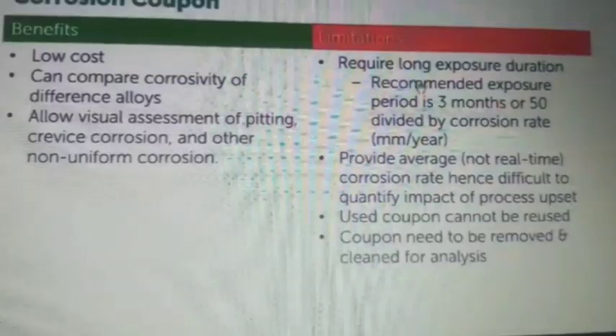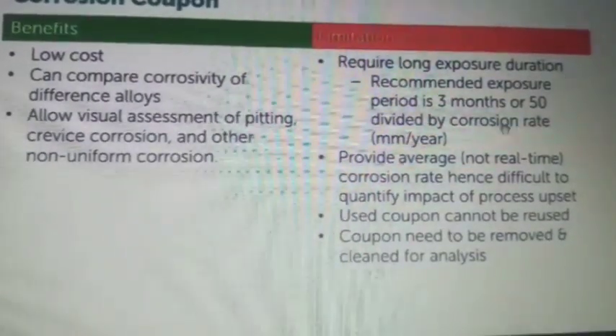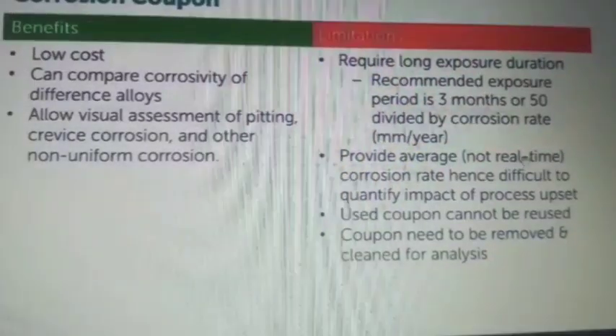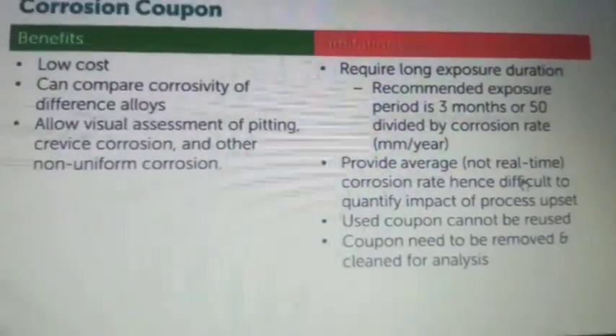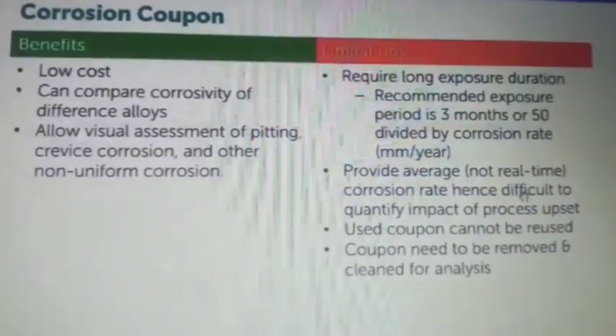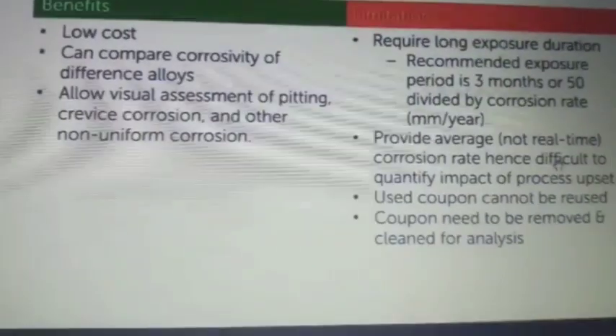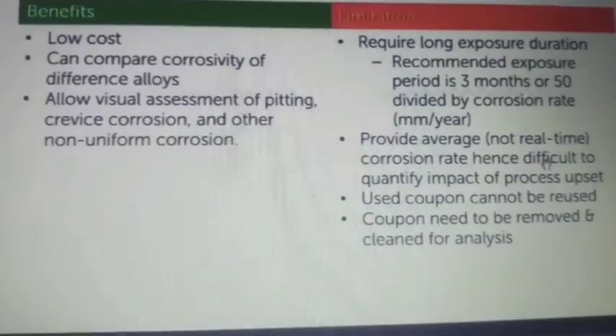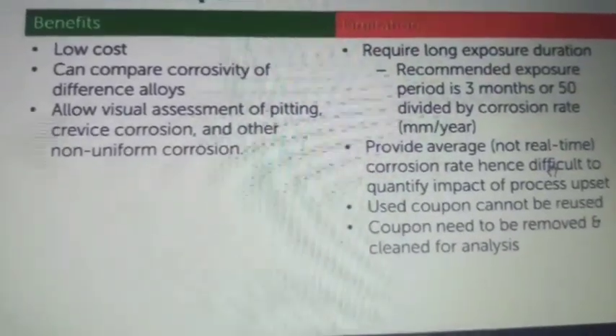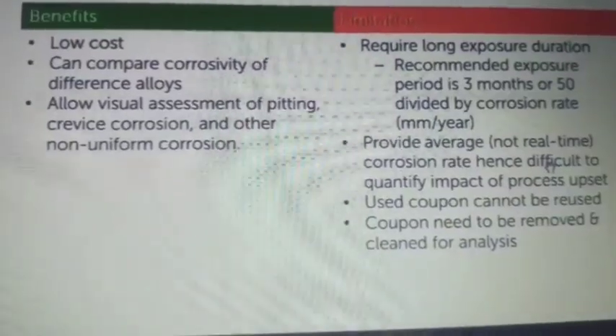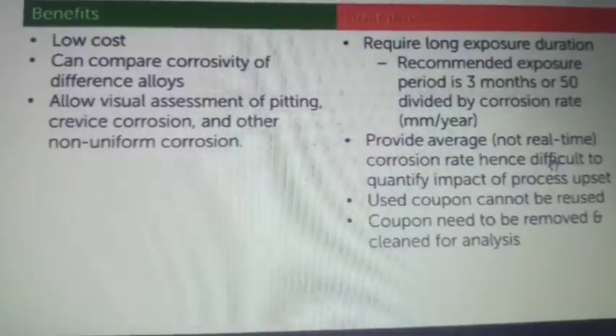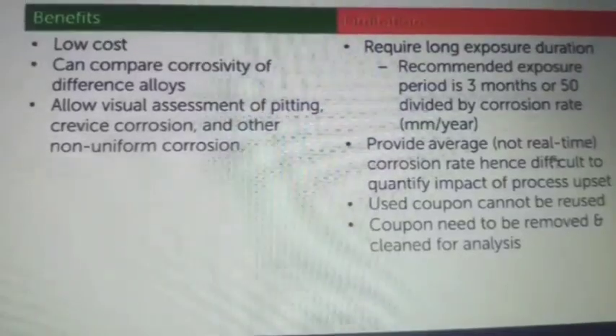So for the corrosion coupon, the limitation is that it requires a long exposure duration. It provides the average corrosion rate and not the instant corrosion rate. Suppose you have no corrosion for 30 days, then a very high corrosion rate for the next 30 days, and in the next 30 days you don't have much corrosion, but some. If you take a coupon, you don't know that in the first month there was no corrosion, in the second month heavy corrosion, and in the third month light corrosion, because it gives the average weight loss over 90 days. You never know when the high corrosion happened and when the low corrosion happened. That is one of the disadvantages of the corrosion coupon.